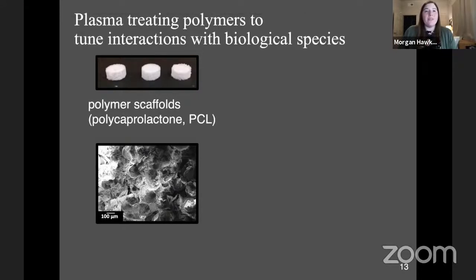So for this research, I fabricated three-dimensional polymer scaffolds. And the idea behind this fabrication was to create a device that mimicked the extracellular matrix. So on the bottom left here, I'm showing a scanning electron microscopy image that demonstrates the interconnected porous structure of this PCL scaffold, which is at least similar to the extracellular matrix in terms of its three-dimensional interconnectedness. So think of this like a very tiny version of a kitchen sponge, okay?